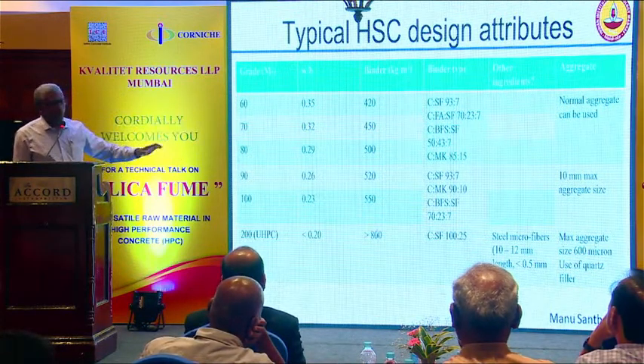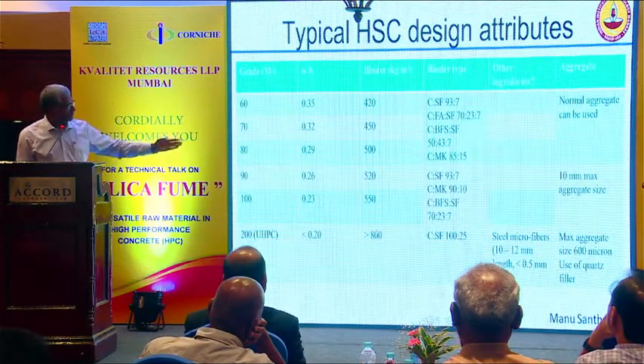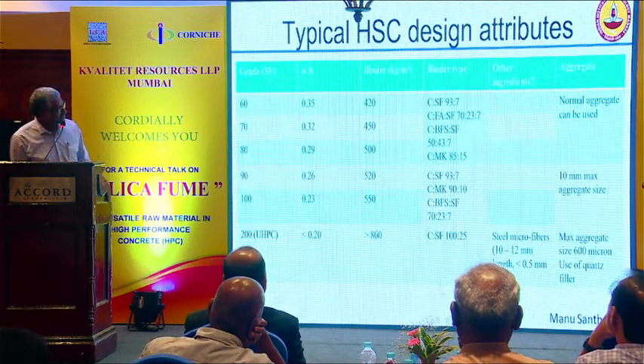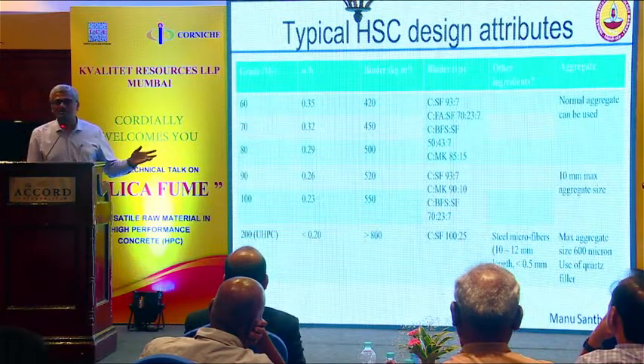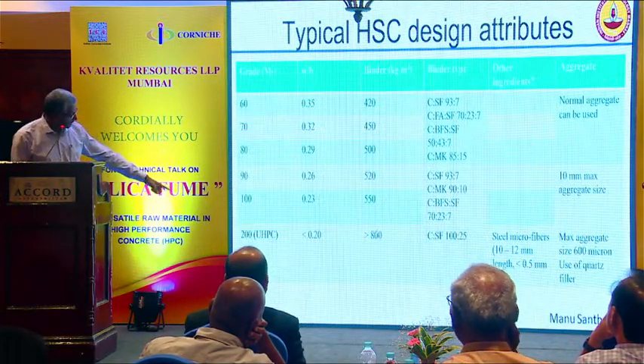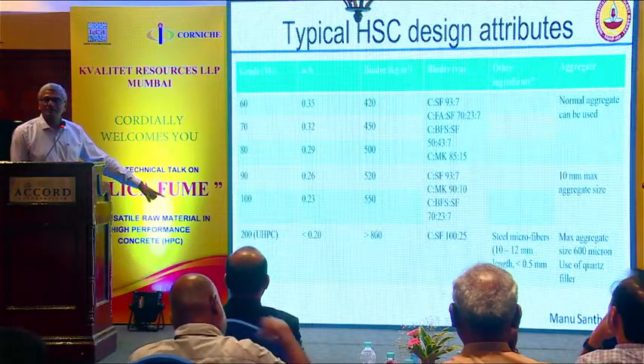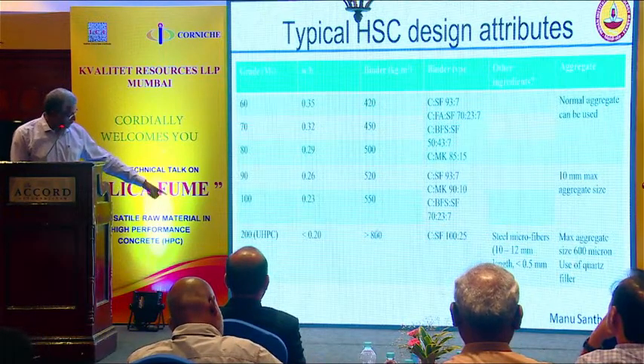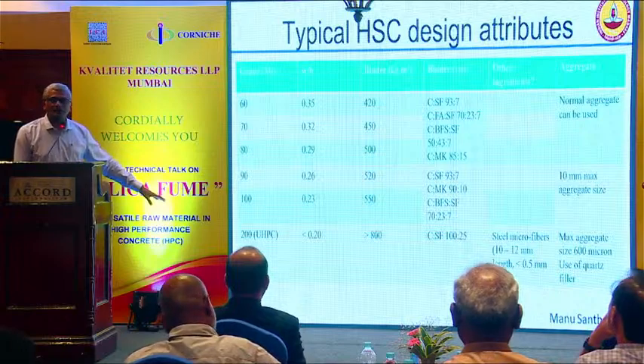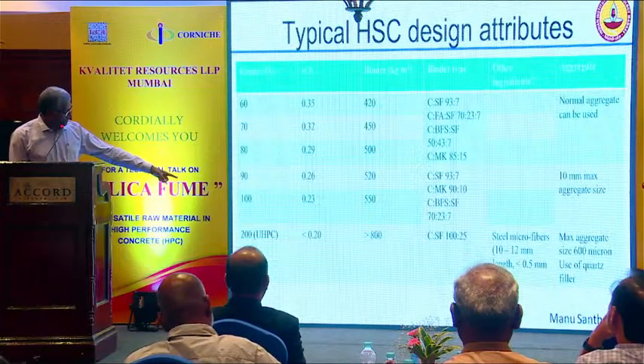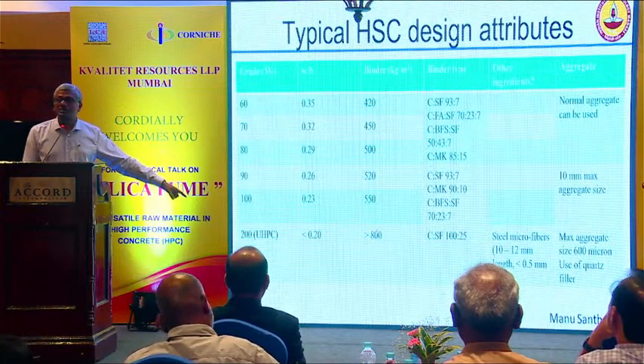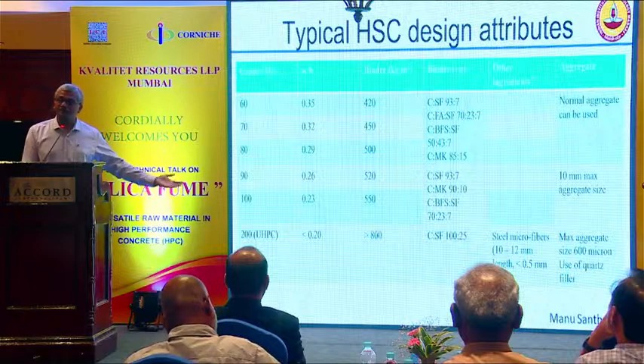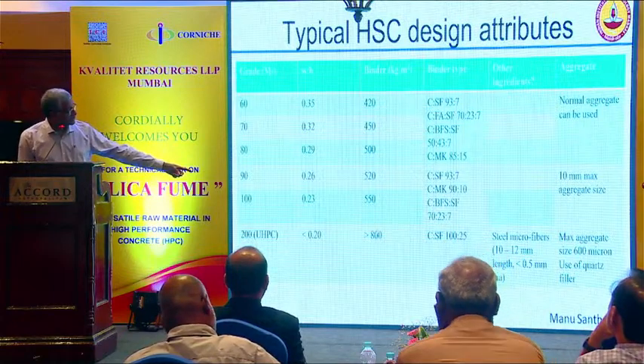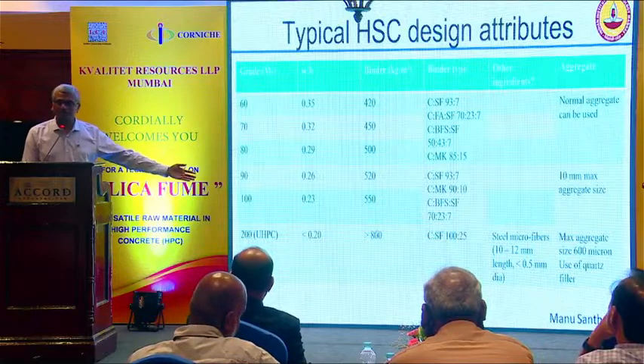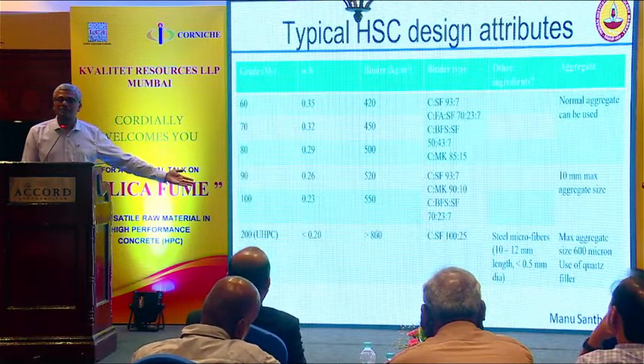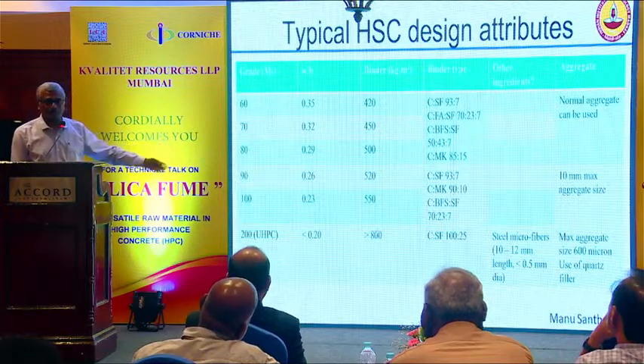So what I've given there is how people generally design with silica fume. As you can notice there, in most of the cases, the silica fume replacement level is around 7% or 10%. But when you come to ultra high performance or ultra high strength concrete, which is sometimes otherwise called reactive powder concrete, 200 megapascal concrete, this is also being produced, where water binder ratio is less than 0.2, 0.15 and so on is used. Sometimes your binder content can exceed, and invariably it will exceed 800 kilograms per cubic meter. You'll go to 1000 also, 1000, 1200 sometimes.